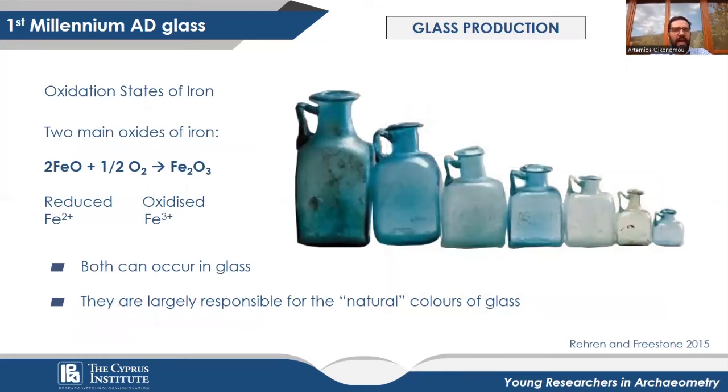This coloration of glass was done unintentionally, since the ancient glass makers were not able to purify sand and extract the iron content. Therefore, iron, which has 2 oxidation states, iron +2 and iron +3, in the sand is responsible for the natural color.